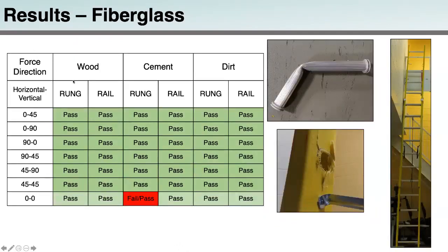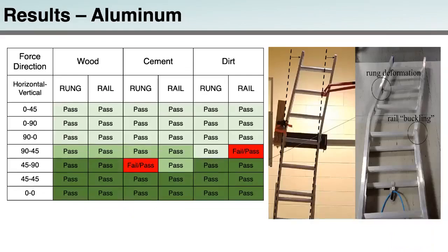So if you look here, this would be an image of what the fiberglass ladder looked like after all testing was completed. So you can see that the one rung here is broken, but it's resting up against a wall here, and you can see there's very little deformation in it, considering that it endured over 40 impacts. In comparison to the aluminum ladder here, which you could see a lot more deformation.